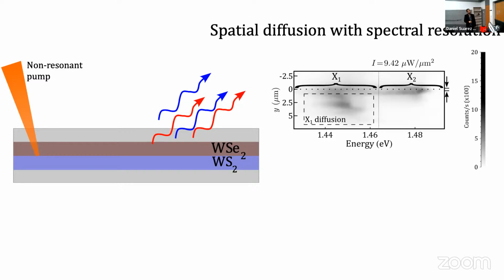This is the kind of figure we can get. We have the diffusion distance in this axis, and the energy in the horizontal axis. So notice how one can pump at y equals 0, and then the population of excitons from singly occupied sites is going to diffuse in the material, and one can observe such diffusion. In this case, for example, we are very close to an edge. The material is very inhomogeneous, so this is not an ideal material by far. So they diffuse in this case downward.